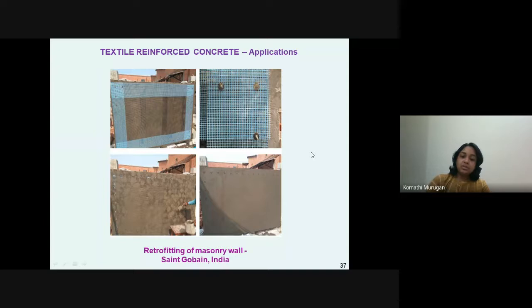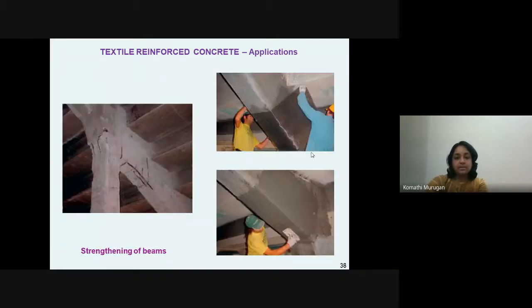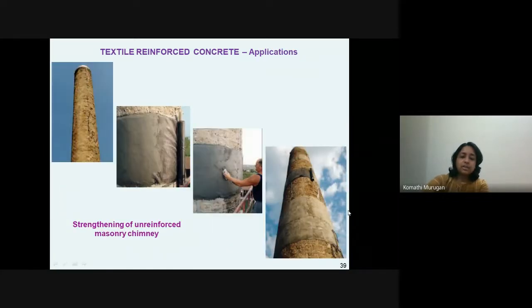Saint Gobain in India is one institute that produces these textiles, but from the fibers, the production happens in France and also in the US. However, they are one point of contact if we want to get these textiles which were manufactured abroad, and they are also into research projects with this TRC. Strengthening of beams. The deteriorated beam is shown here. The mats are placed and they are closed or finished. Strengthening of an unreinforced masonry chimney, where we find the crack here in the chimney. The textiles are wrapped around, and they are closed with a mortar here.